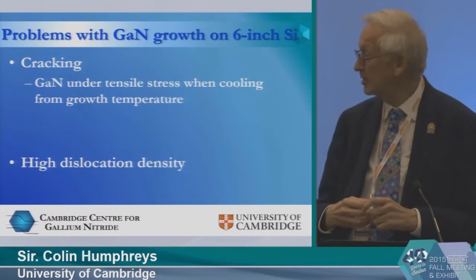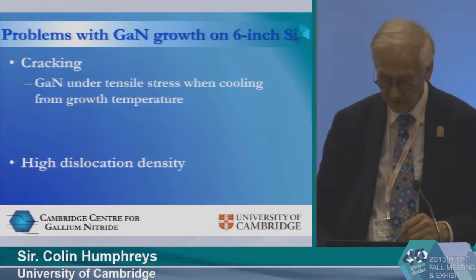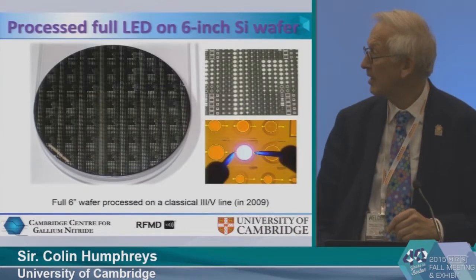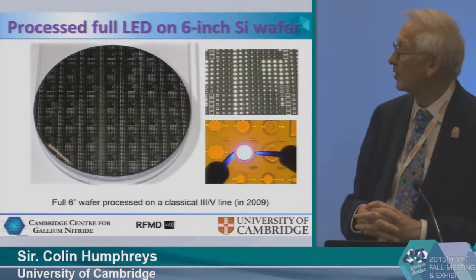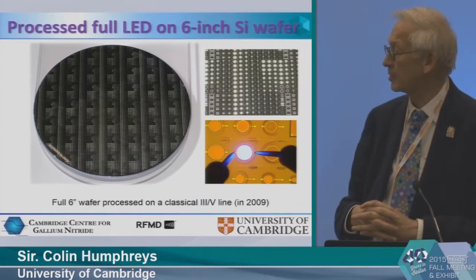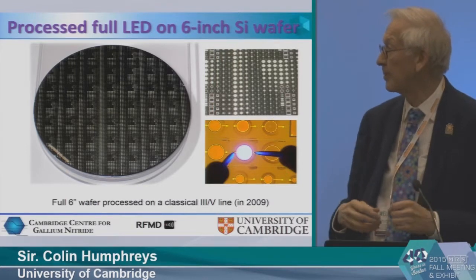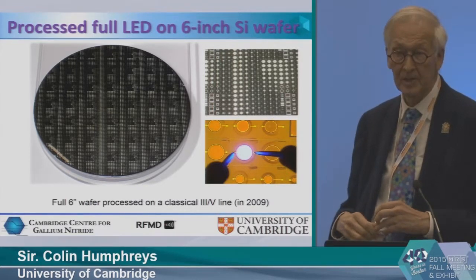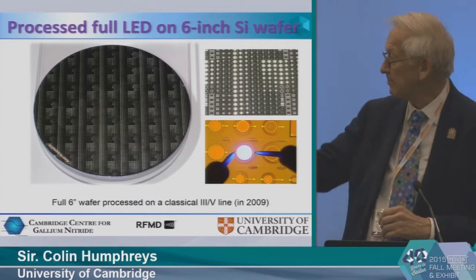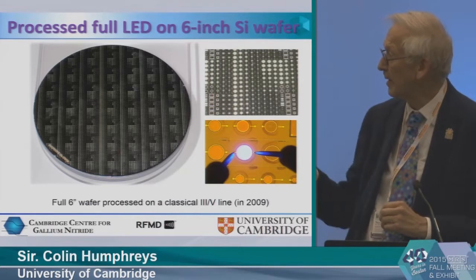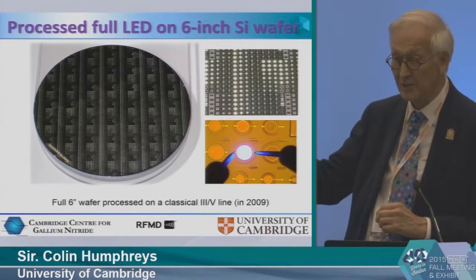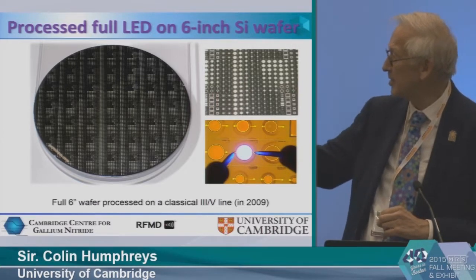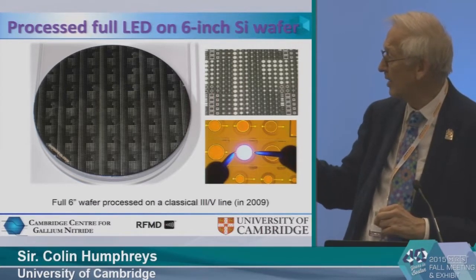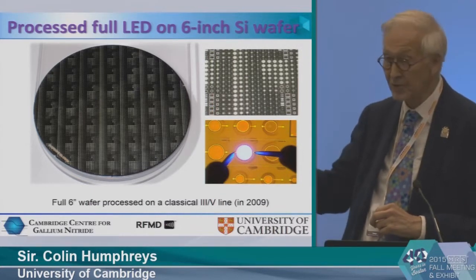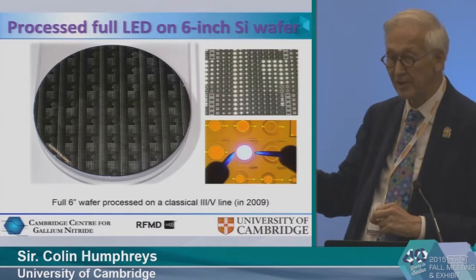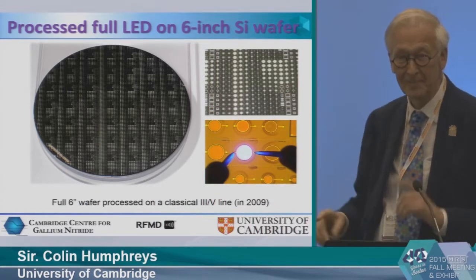And we can now routinely grow gallium nitride LEDs on 6-inch silicon with no cracks at all and with relatively low dislocation density. And this is an example of the first fully processed LED on a 6-inch silicon wafer in the world, which the growth was done by my group in Cambridge, and then it was processed by RFMD on a 6-inch processing line. And the left-hand side shows a 6-inch wafer, totally crack-free. There's a variety of different LED sizes on that, so it's a sort of test wafer. And then the top right-hand side shows a number of these LEDs of different sizes, and the bottom diagram shows a current being passed through the LED. It's actually emitting blue light that's so brilliant it's saturated the detector, so you just see it as white light. It's actually blue light being emitted.